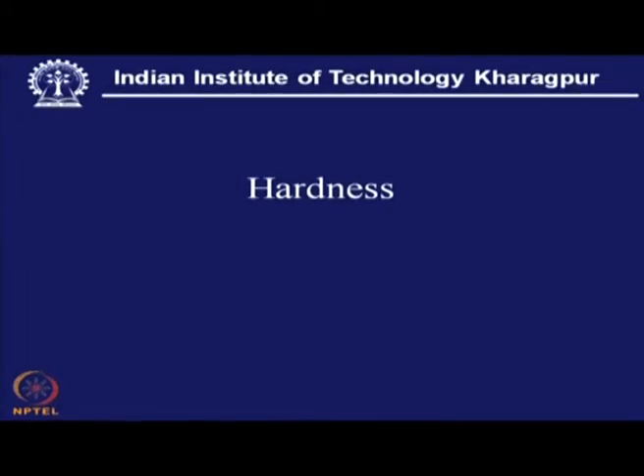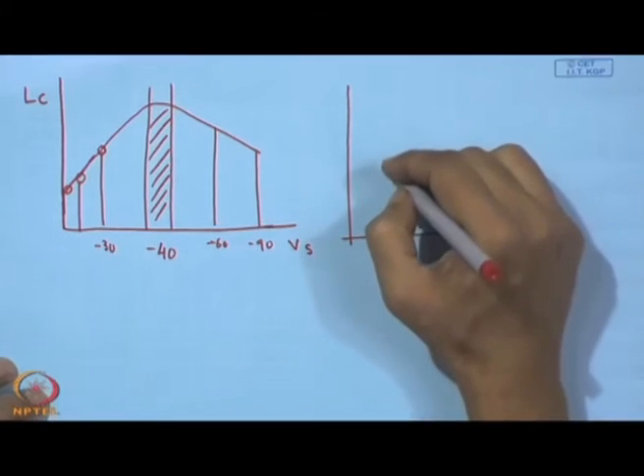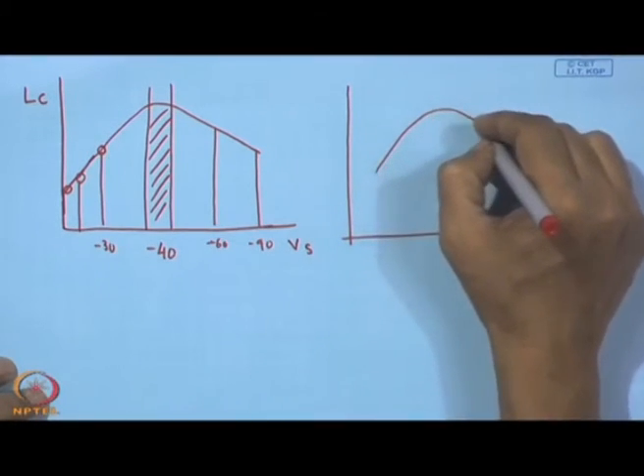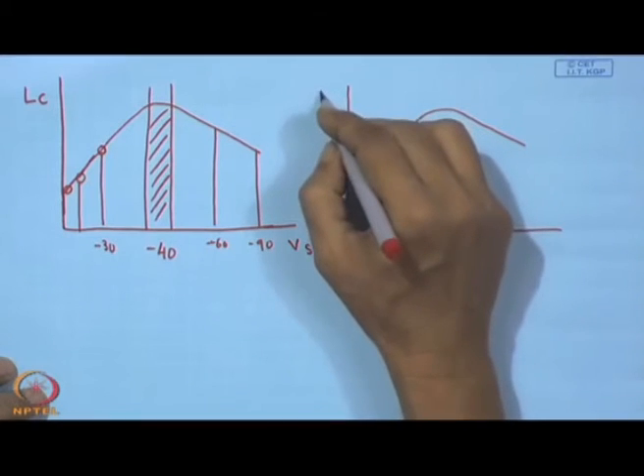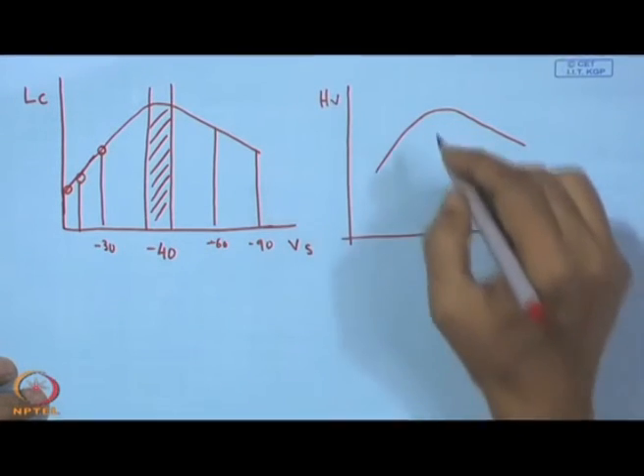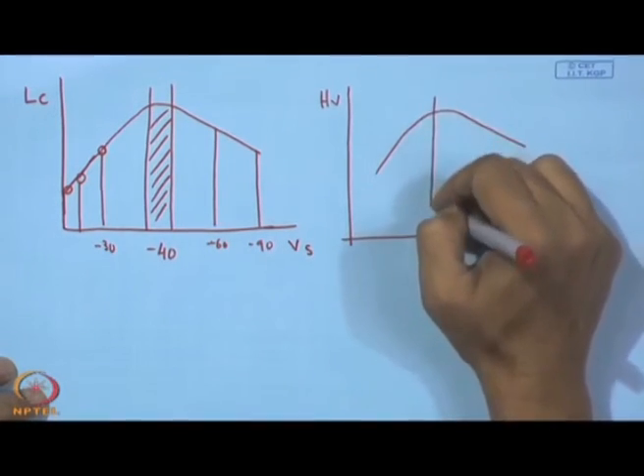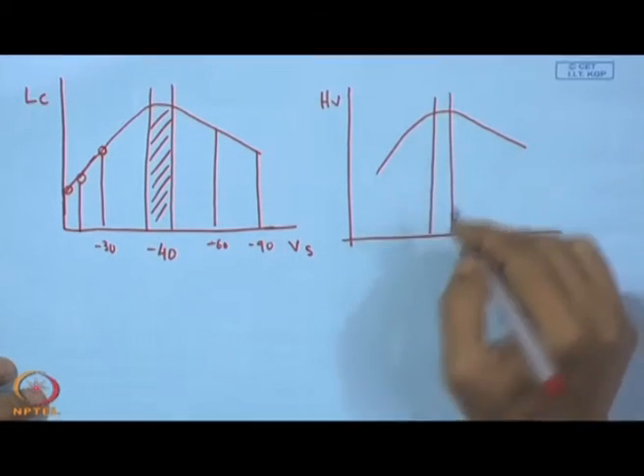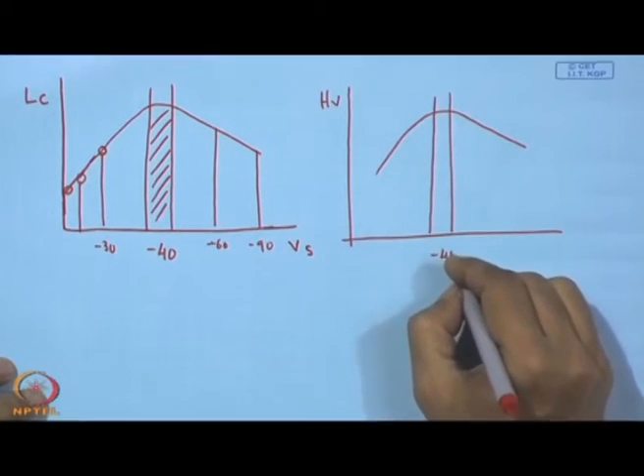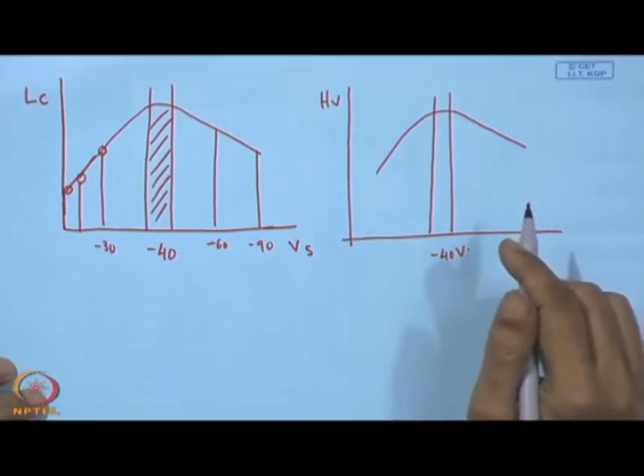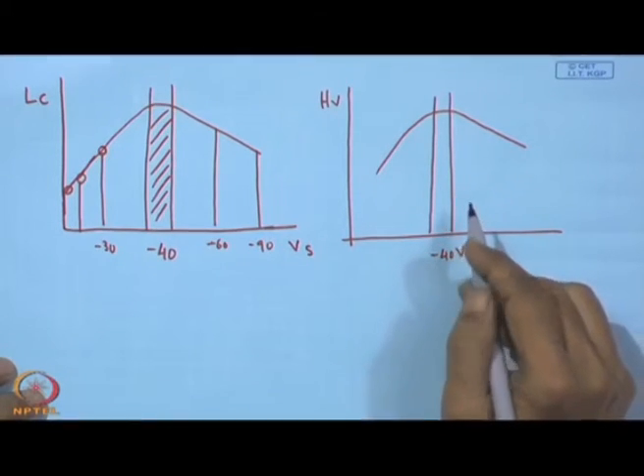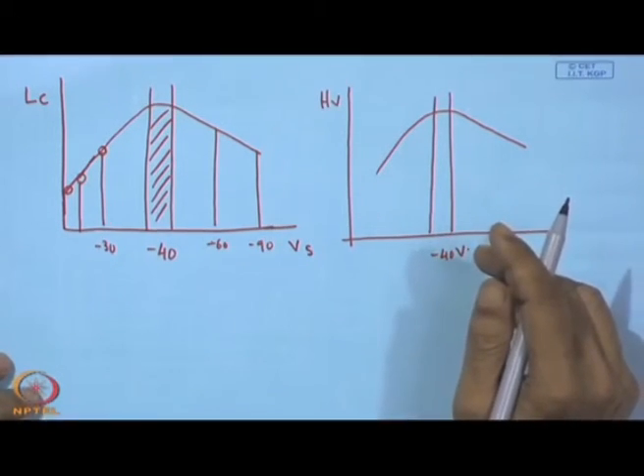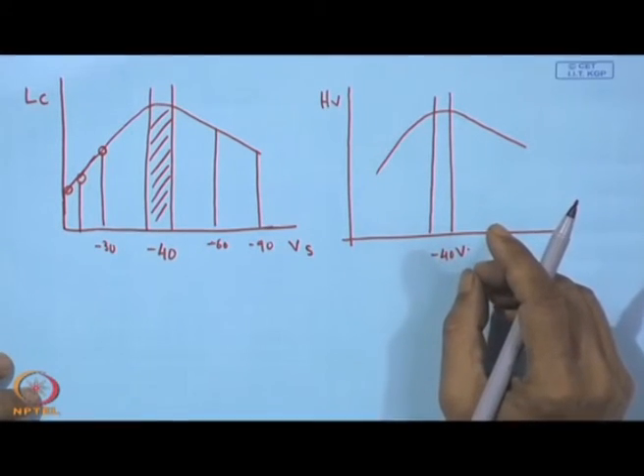Hardness. Now, this hardness also can have a curve like this with substrate bias, and here also a zone we may come across around minus 40, and this is where we have densification of the coating, closing all the pores and voids.